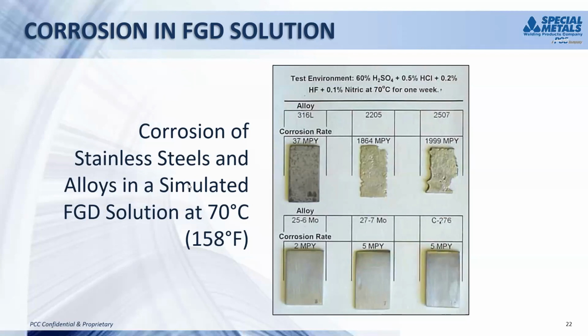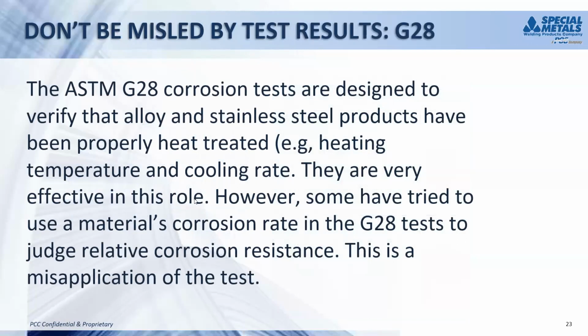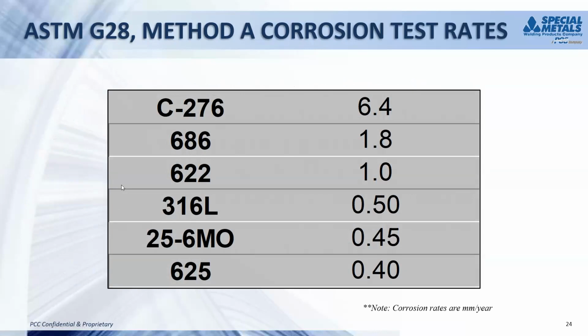Those samples have just basically corroded away, and this is only after a week exposure. The super austenitics and the C276 all exhibited low corrosion rates. The next slide, I would caution you that some people have tried to use existing corrosion tests to compare materials for FGD service. And this is a misapplication of the test, and it just simply doesn't work. The next slide shows the general corrosion rates that you see with an ASTM G28 method A corrosion test.